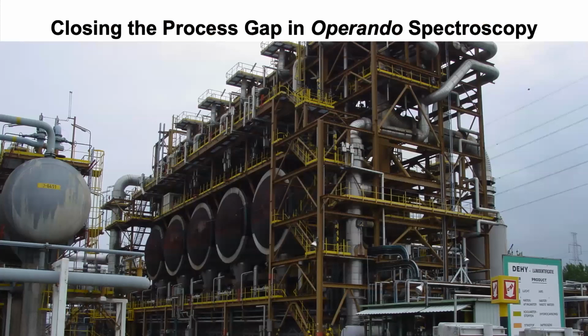And those who follow our work, they know that we have been working a lot on light alkane dehydrogenation, as the chairman here is also working on light alkane dehydrogenation. We initially worked a lot on chrome alumina still, but it's now diverging to platinum, gallium, whatever else. This is a reactor in the Antwerp harbor, or near the Antwerp harbor, it's Kallo actually, where you see the Houdry process, 5 reactors filled with a huge amount of chrome alumina catalyst powders.